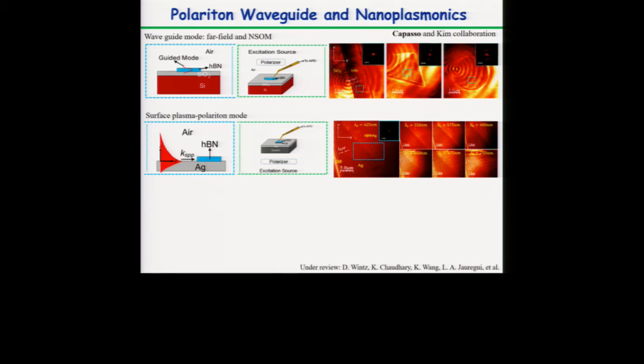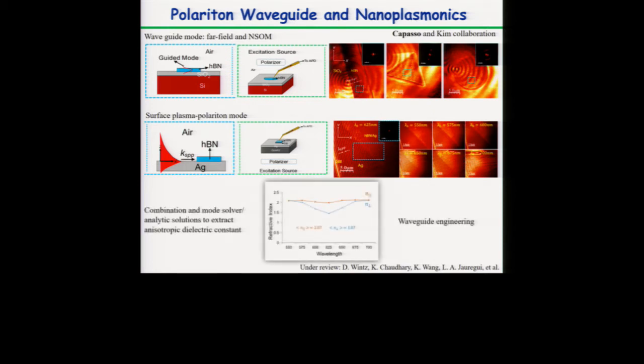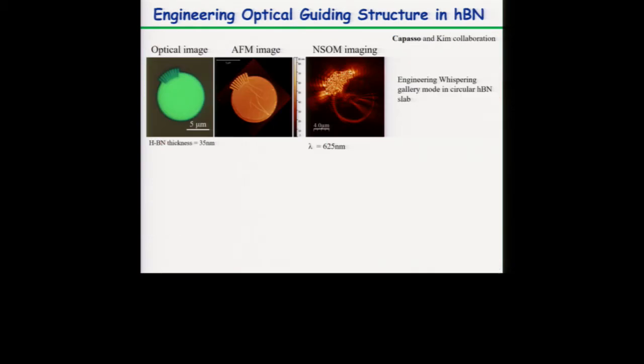Either this is in plane, or if you use surface plasmon polaritons like silver, you can also obtain out of plane, because as I mentioned, the SPP has an out of plane electric field. So in collaboration with the Capasso group, we have obtained the refractive index for boron nitride in plane and out of plane with some precision, right? So it's all based on the change of the refractive index of the material.